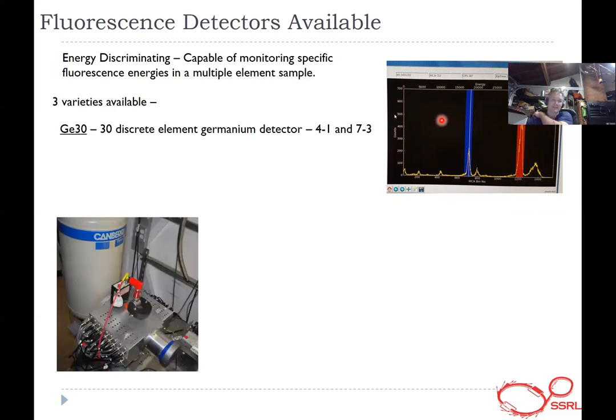We have a 30 element discrete germanium detector, and these are available at 4.1 and 7.3. And these are really nice. They behave really well. Since the elements are discrete, you don't get much crosstalk between the unique detector elements. They're really new, so their rise times are good, their noise is pretty low. They do saturate at around 100,000 counts per second. So that's something you take out, and that's something you'll discuss with your beamline scientist.